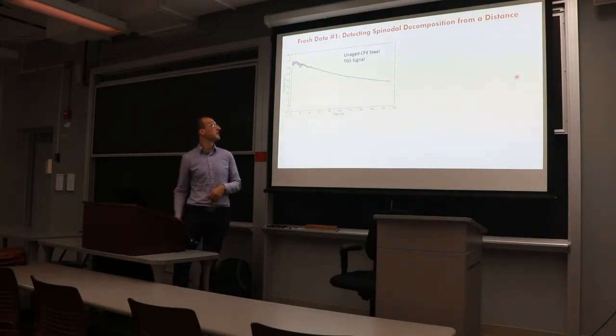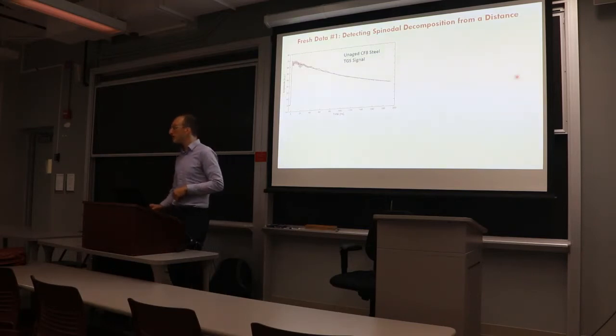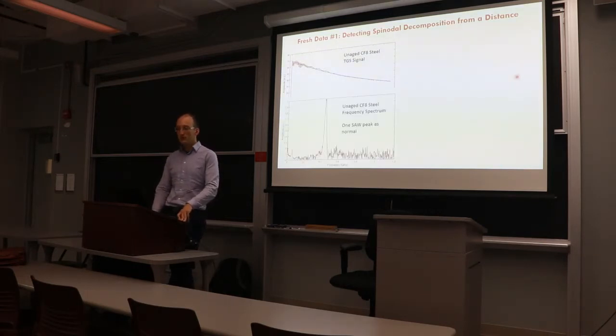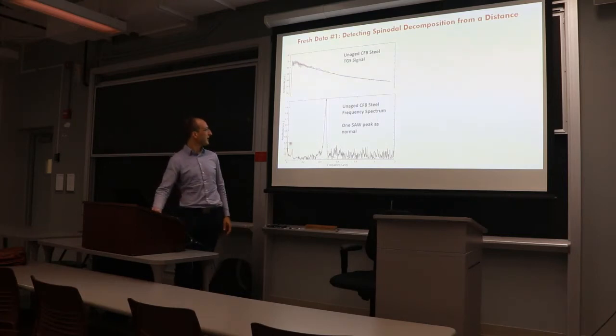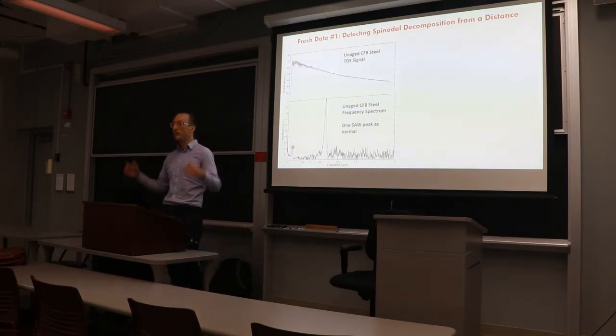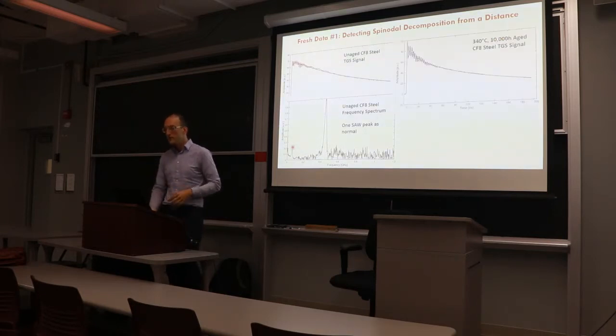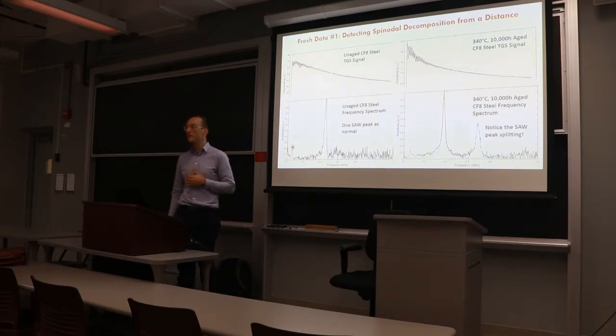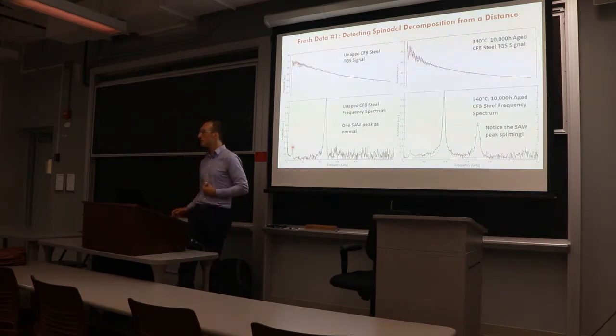This is what a TGS signal looks like from an unaged cast austenitic stainless steel. I would say on the grand scheme of things, pretty boring. And when you take a Fourier transform to look at the acoustic wave modes, pretty boring. The only other thing you see here, that thing, is the air acoustic wave from the lasers crossing in a hemisphere of air in front of the sample. When you age the sample, however, it may look the same in time space, but in frequency space, something else happens. You get surface acoustic wave peaks splitting, which we can't see any evidence of having happened before.